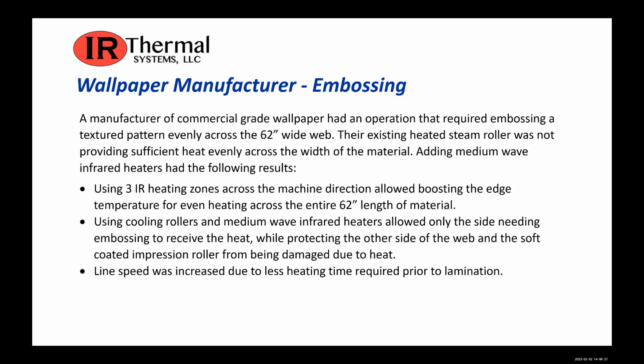So we chose to add medium wave infrared heaters with the following results. Using 3 infrared heating zones across the machine direction allowed boosting the edge temperature for even heating across the entire 62 inches length of material. Using cooling rollers and medium wave infrared heaters allowed only the side needed embossing to receive the heat, while protecting the other side of the web and the soft coated impression roller from being damaged due to the heat. Line speed was increased due to less heating time required prior to lamination.